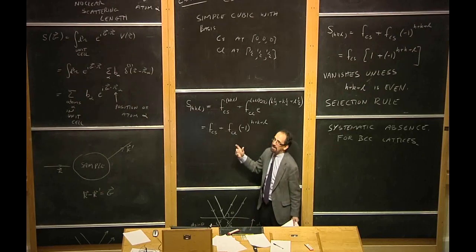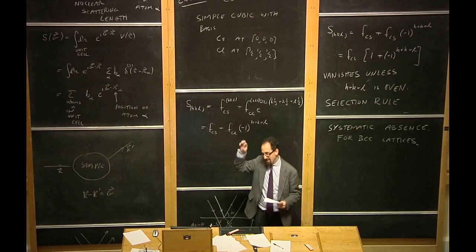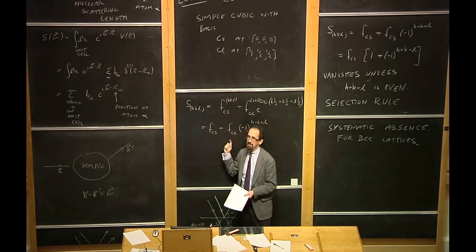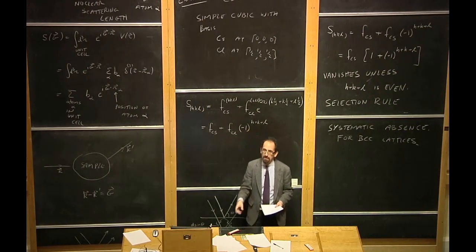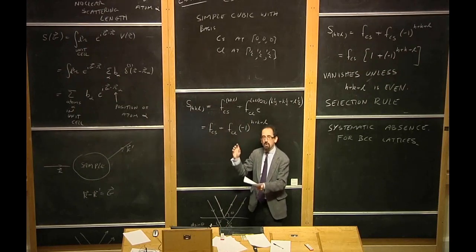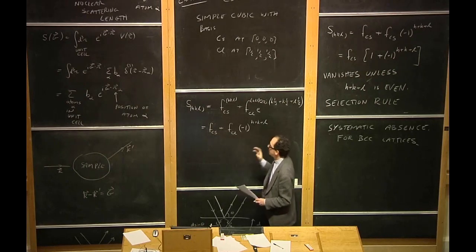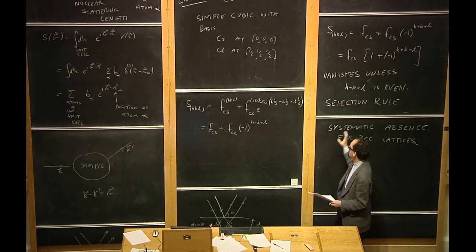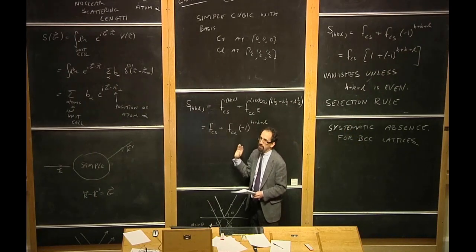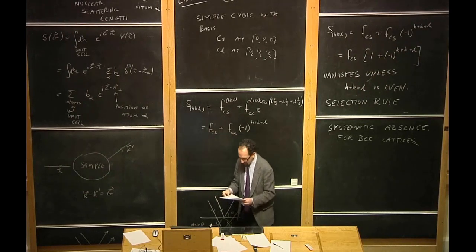It's cesium iodide. If you replace chlorine with iodine, which is two spaces under it on the periodic table, the iodine has atomic number 53 and cesium has atomic number 55. So the cancellation between these two would be almost exact. I mean, only within a few percent you would have slight non-cancellation. So it's very easy to make the mistake and look at the data and think that you have a BCC lattice because you think there's a systematic absence. But if you look at it much, much more closely, you discover that, in fact, it's not perfectly canceling. Okay? Everyone happy? All right.